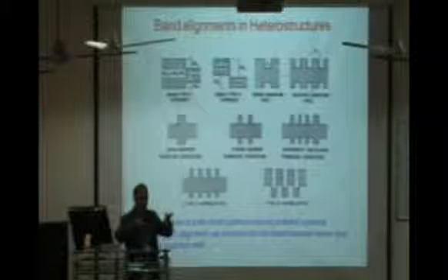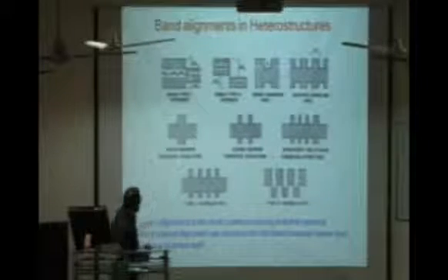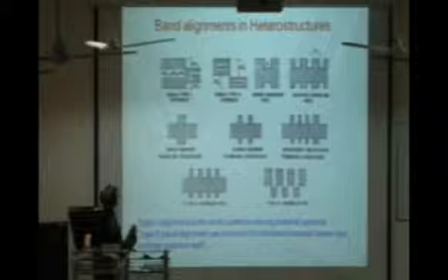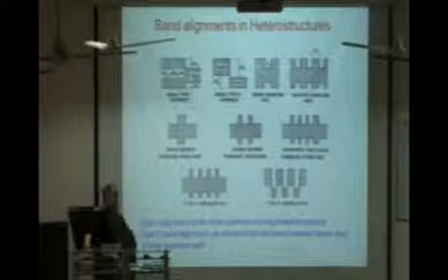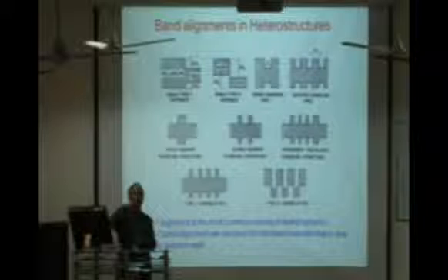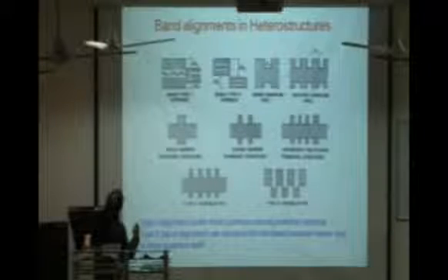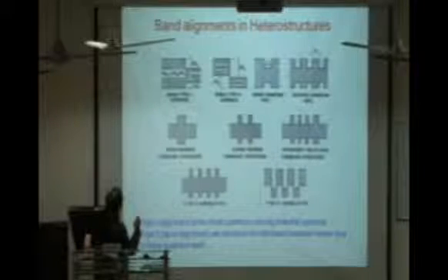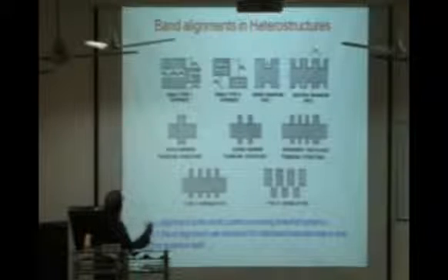Okay, so I'll come to this also. Till now we have seen that if you have one barrier, one high band gap semiconductor and a low band gap semiconductor, we make heterostructures. Heterostructures can be of different types. It can be type 1. In this example, I have taken gallium arsenide, a very common example, as the low band gap semiconductor, and gallium aluminum arsenide of a particular composition as the high band gap semiconductor. They have been chosen because they have the same lattice constant, so one can be grown on another without any defects experimentally. And as you see, we have a conduction band offset and a valence band offset. So our quantum energy states have to be confined within these offsets. If I put one more barrier on this side, we get what is called a quantum well, that single quantum well that I was showing.